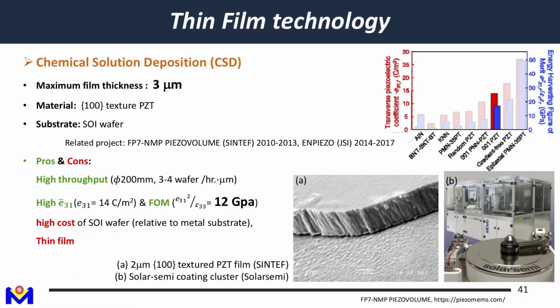because of the following fabrication difficulties. The other thin film technology, this is actually the mainstream piezo MEMS process for now. It's called CSD, chemical solution deposition. It's an improved version of the sol-gel process, and it's already quite mature. You can actually buy a machine that does this kind of CSD material with a complete recipe, and it's also so-called textured PZT, aligned to the 100 axis of the silicon substrate, and it can generate quite high performance piezo film. The figure of merit is about 12 gigapascal, and the disadvantage is it typically requires an SOI wafer that's quite expensive. And also the thickness is limited to about 2 to 3 micron.